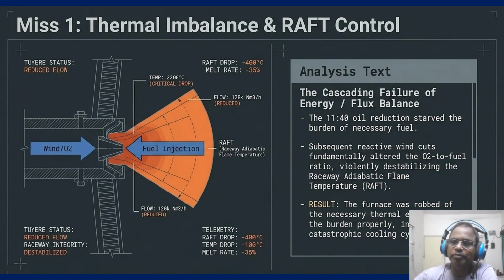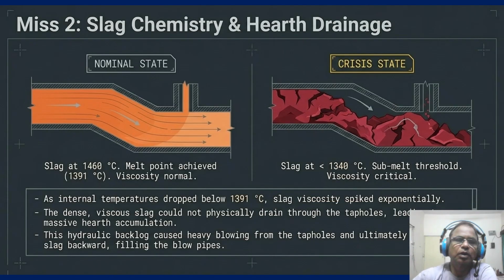So coming to our miss number two, and miss number two is about the slag chemistry and hearth drainage. So look at the normal versus crisis comparison on slide 10. In the nominal state on the left, slag flows smoothly at 1460 degrees centigrade, but on the right, in the crisis state, look at the jagged red mass blocking the flow. As the temperature dropped below 1391, the sub-melt threshold, slag viscosity spiked exponentially.